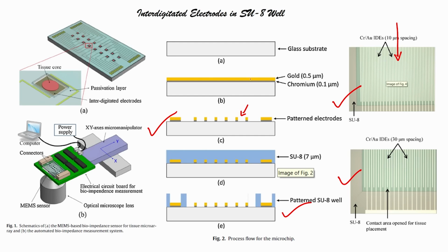After spin coating photoresist we are pre-baking at 90 degrees. After pre-baking at 90 degrees we are loading the mask. After loading the mask we are exposing the wafer with UV light. After exposure of the wafer we are developing the wafer. After developing the wafer we are post baking the wafer. After post baking we are removing the gold and we are removing the chrome. When you remove chrome and gold, after that we are stripping off the photoresist with acetone, and you get section C, right. This whole process we do to get section C.